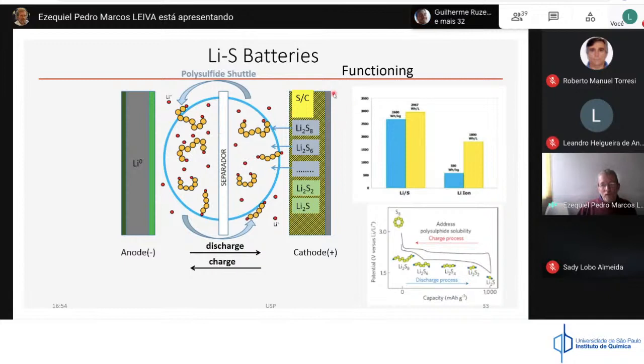Well, you may ask why people are interested in lithium sulfur batteries instead of lithium-ion batteries, which has to do with the specific capacity. Here you can see from the blue curve the specific capacity per unit mass, and you can see that the capacity of lithium sulfur batteries, which are denominated post-lithium technology, is considerably larger than the capacity of the lithium-ion battery. This is one of the reasons that people are trying to switch. These batteries are still not ready, and there are many improvements to be made before they can work. This is one of the problems, the polysulfide shuttle. But these batteries are very promising from the viewpoint of storage capacity.